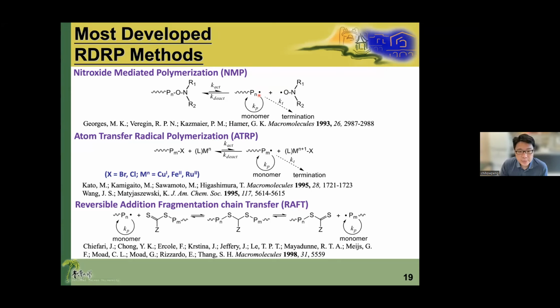And in ATRP, actually the mechanism is the same. Okay, they have the organic compound to deactivate radical polymerization and use this equilibrium to control the radical concentration. However, with the organometallic complexes, you can select the ligand, you can change the metal, you can switch the halogen, so that you have a better way to tune the equilibrium of the system, so that ATRP was known to be suitable for more monomers.